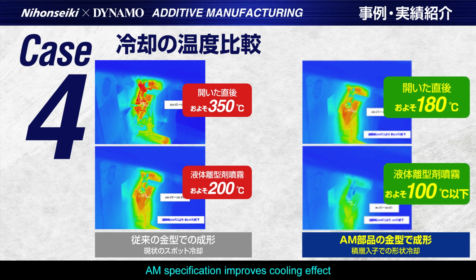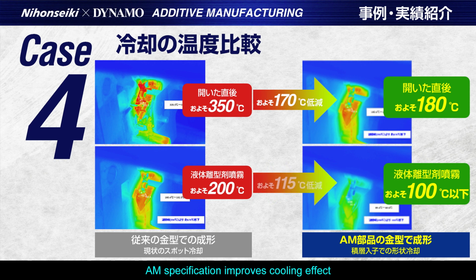After the AM component was installed in the mold, the upper image shows the temperature after casting, which is about 180 degrees Celsius, reduced by about 170 degrees Celsius. The lower image shows the temperature after spraying the mold release agent, which is about 100 degrees Celsius or less, reduced by about 115 degrees Celsius. This shows that the temperature of the conformal cooling method after spraying is lower than the conventional type after spraying.